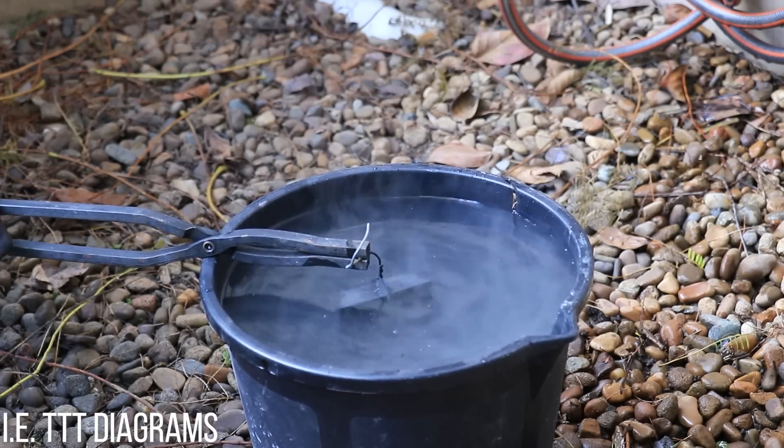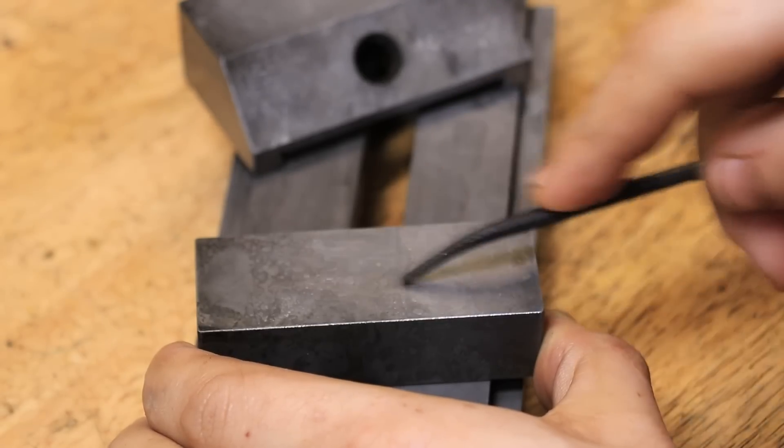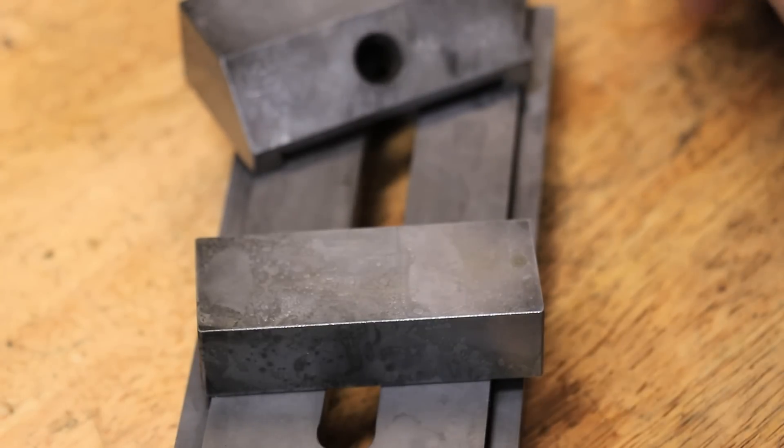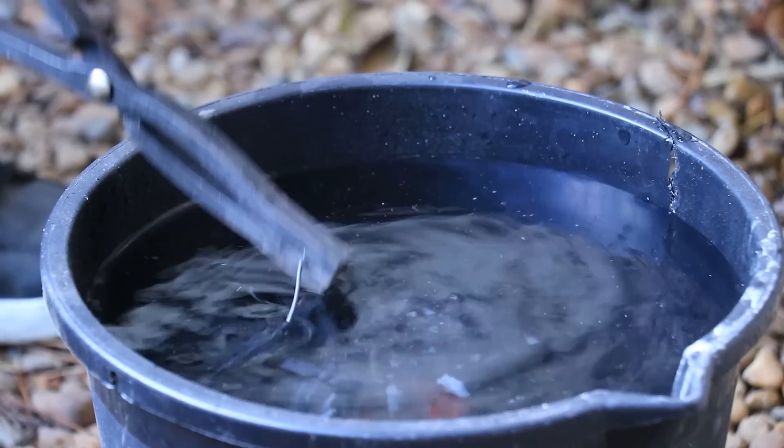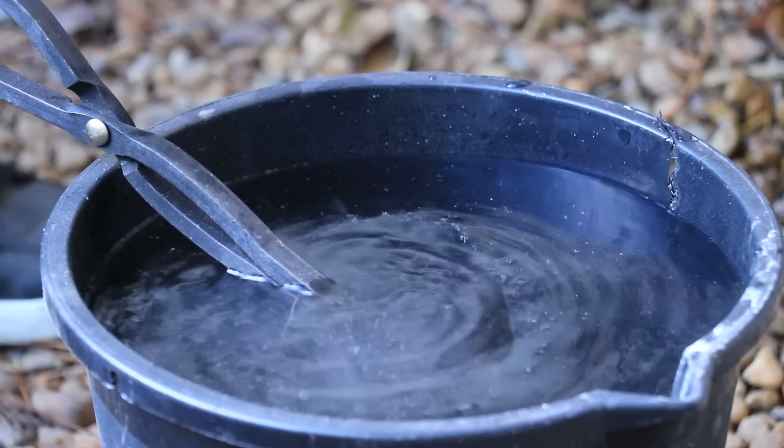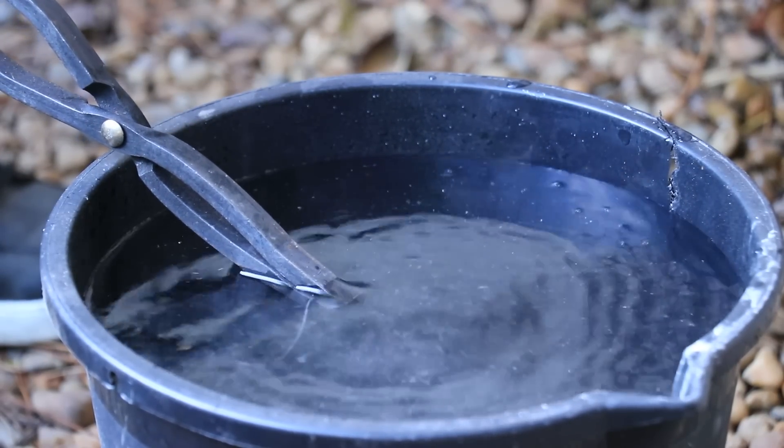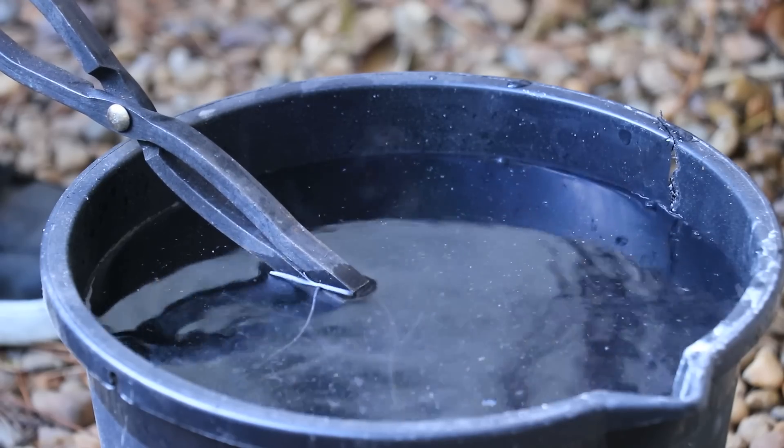With this method, getting a hardness of 65 Rockwell C is pretty easy. The problem that you're going to experience is when you cool stuff at such a fast rate, if you don't cool it evenly, there is a big risk that you're going to warp the part and throw it out of tolerance.